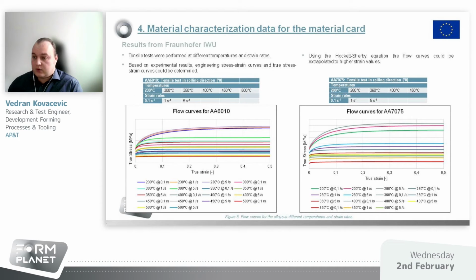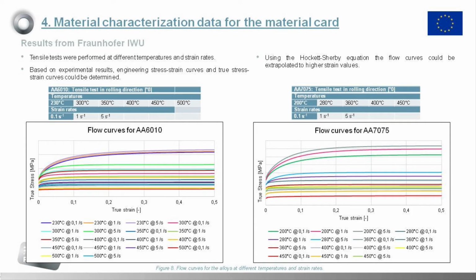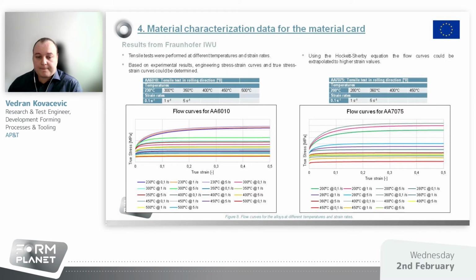Fraunhofer performed tests for AA6010 and AA7075. They were performed at different temperatures and strain rates according to the tables in order to obtain the data needed to describe the plastic behavior in the material at elevated temperatures. By implementing the true stress strain curves gained from the experimental results into the Hockett-Sherby equation, it was possible to extrapolate flow curves to higher strain values for the alloys.